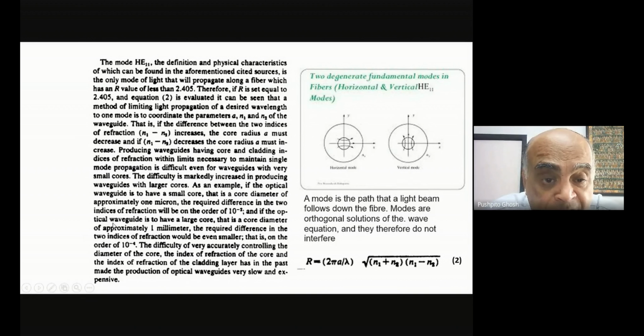And if the optical waveguide is to have a larger core, that is a core diameter of approximately 1 millimeter, the required difference in the two indices of refraction would be even smaller, that is on the order of 10 to the power minus 4. That is the kind of difference between N1 minus N2 that you will have to have reproducibly if you are going to have a core diameter of even 1 millimeter.